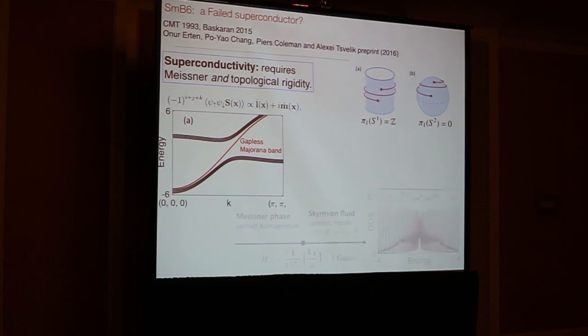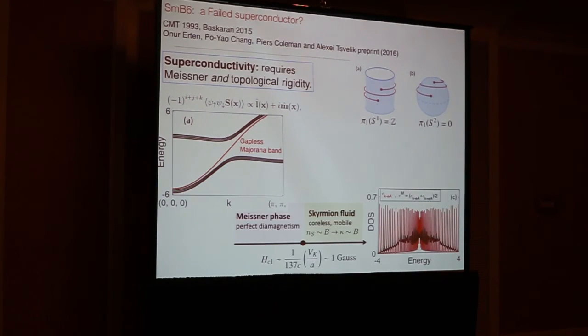And these guys are rather interesting, and in fact a very simple, dumb calculation of the spectrum in the presence of a vector potential gives you this quantized spectrum you see here in red. And basically the idea is that this gapless Majorana band, although the linear in vector potential coupling vanishes, and therefore they're neutral, the quadratic in vector potential part survives, if only you can make it gauge invariant.